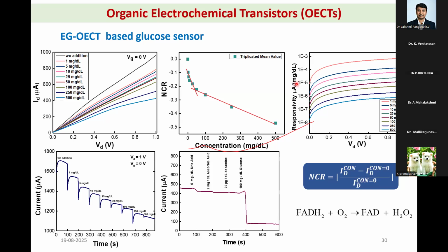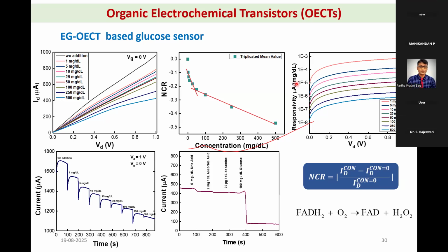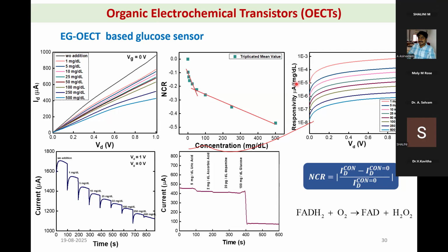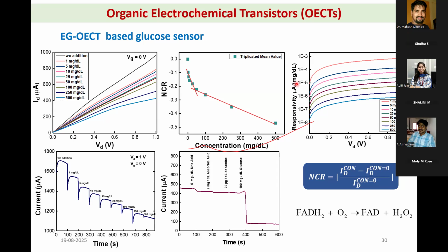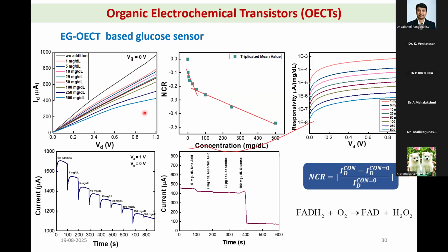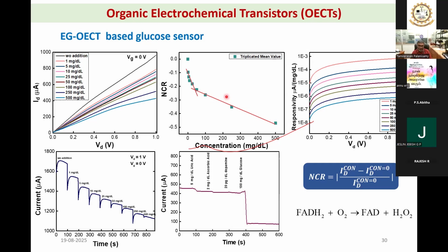The difference here is that in the previous case we biased the gate electrode. Here we have not biased. It is simply working as a non-biased gate. Only source and drain is biased. Gate potential is simply because of the glucose oxidation happening at the surface. And that itself is giving the change. While you change the glucose concentration, you are seeing the clear change in slope of this IV characteristics, and you are also seeing the change in NCR values. So all these are only because of the glucose. There is no bias at all.